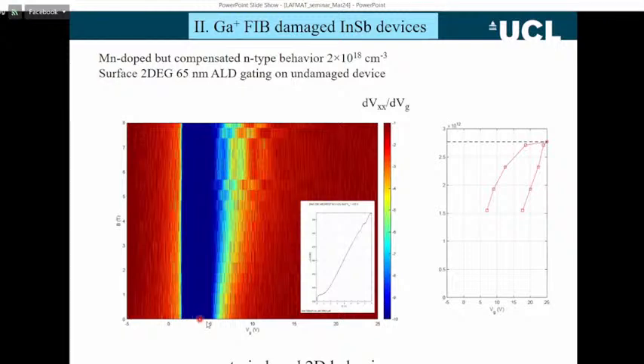And what happens with a positive gate voltage is we induce a charge at the surface. So we just have a surface conducting layer. The rest of the device is kind of disordered. It's got the manganese doping in there. And if we look at a simple, this is fixed gate voltage 25 volts. If we measure the device resistance as a function of magnetic field, we see this kind of increase in the magnetoresistance and then this oscillation. And this oscillation is the Shubnikov-de Haas effect.